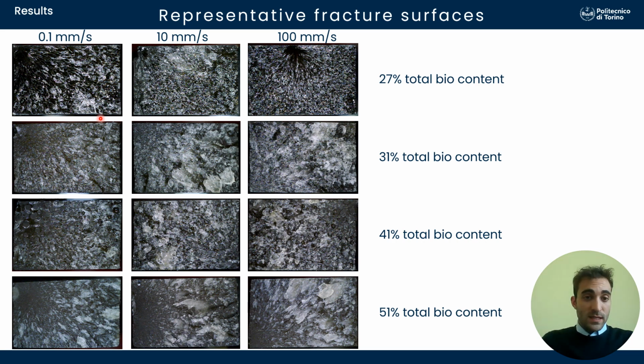Overall, we can say that the failure happens due to the presence of a void, for example, in the specimen of 27% total bio content tested in quasi-static conditions. And this can also be verified by means of the digital image correlation system.